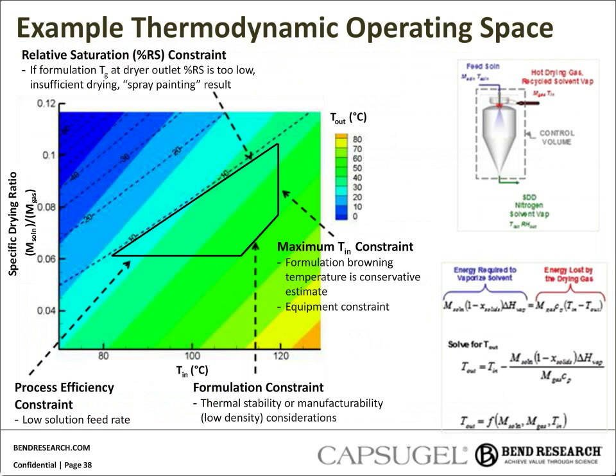So this graph shows a thermodynamic operating space based on simple mass and energy balance equations that are summarized there on the right-hand side of the slide. On the x-axis is the drying gas inlet temperature, and on the y-axis is a ratio of the spray solution feed rate to the drying gas flow rate. We use this ratio, which we've defined as a specific drying ratio, so that we can plot multiple spray drying scales on the same plot. But since drying gas flow rate is essentially held constant at each scale, you can think of this y-axis as a spray solution feed rate.